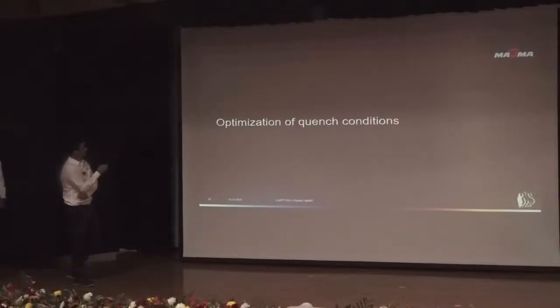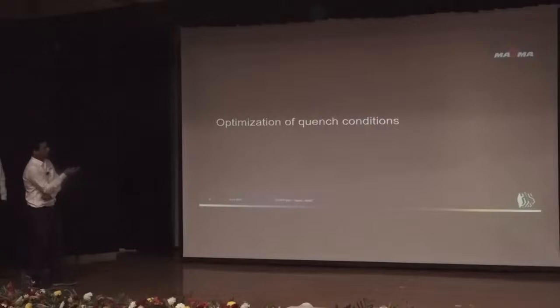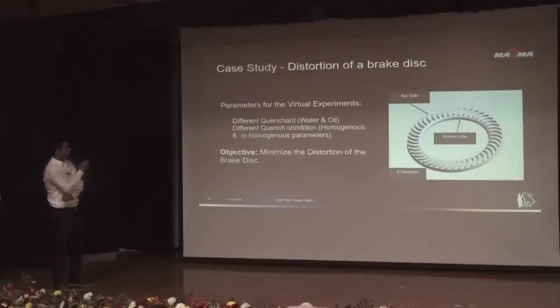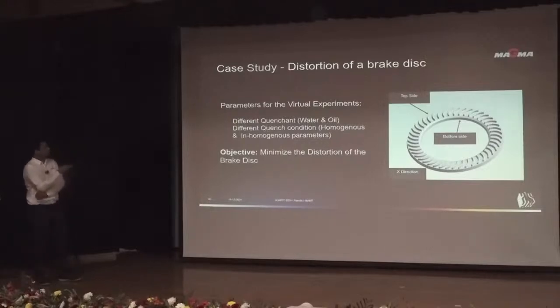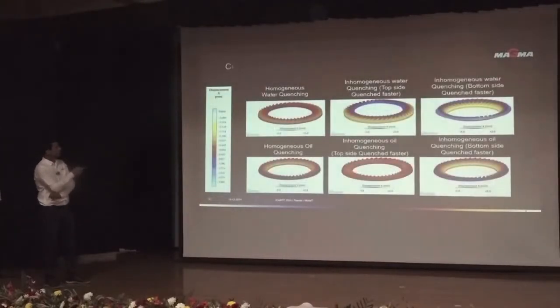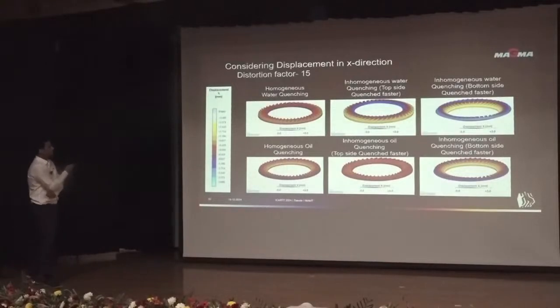Another thing we can analyze in stress is when we quench the castings. So what do we get? This is a ring brake disc. We are going to use 2 different quenchants, one water and one oil, and 2 different quench conditions, one homogeneous and the second inhomogeneous. The objective is to minimize the distortion during the quenching process. These are the 6 combinations that we get: homogeneous water quenching, inhomogeneous water quenching, and the results of those, and with oil also.